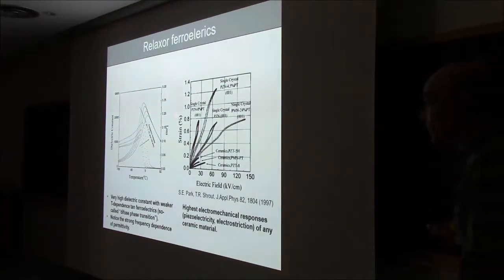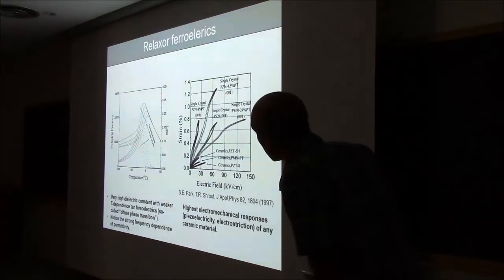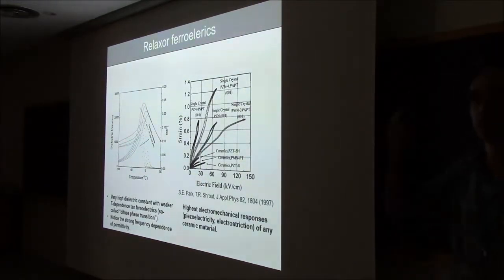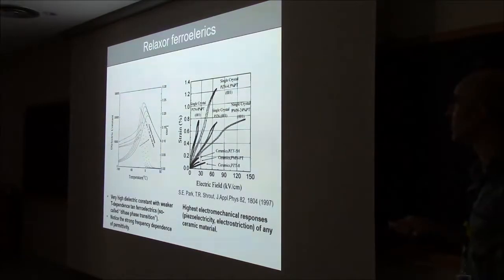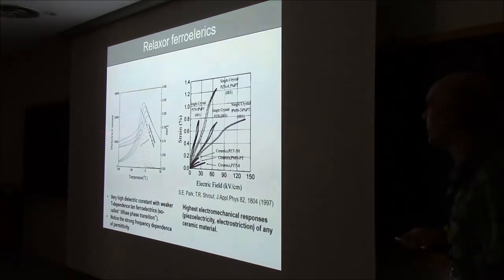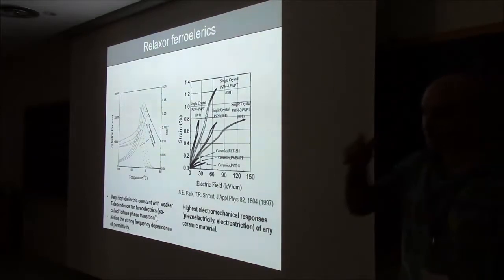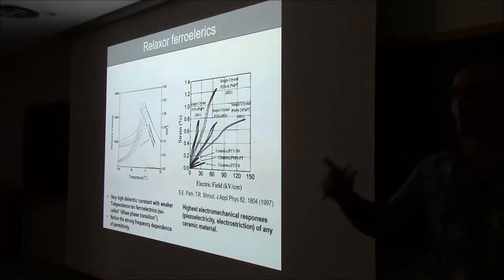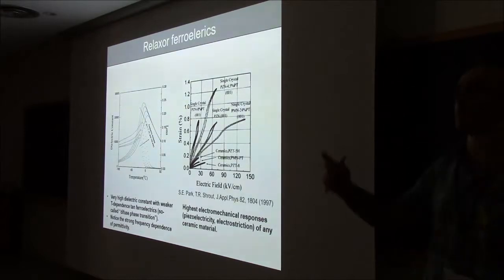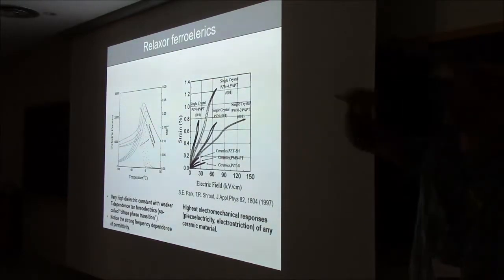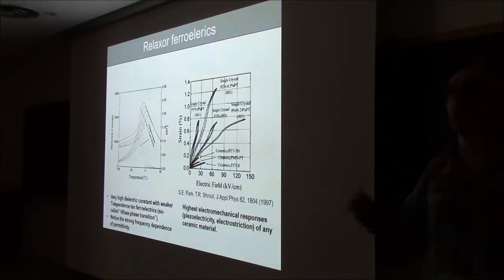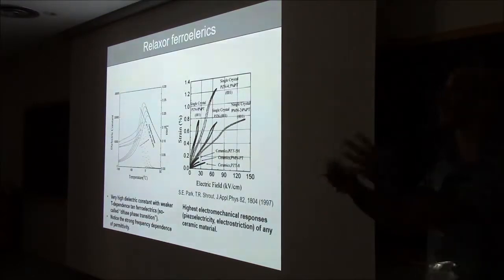And they are very useful because they have a very high dielectric constant that is less temperature dependent than a normal ferroelectric. If you remember in barium titanate, this transition was super sharp. Here it is more rounded. It is frequency dependent because the ability of a cluster to respond to your AC field depends on the size of the cluster. And because you have a distribution of cluster sizes, you have some clusters that respond at low frequency but not at high frequency. So at high frequency, you measure a lower dielectric constant than at low frequency.